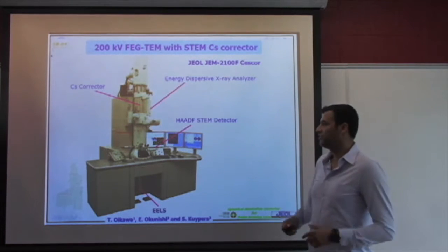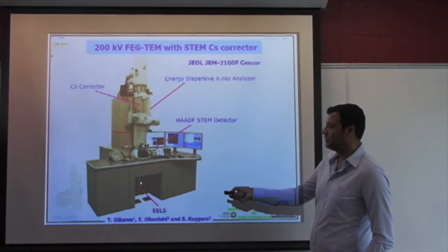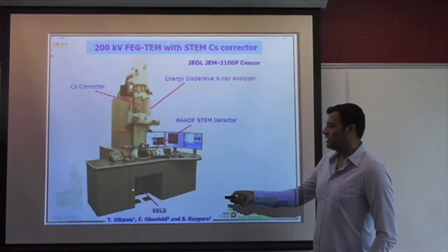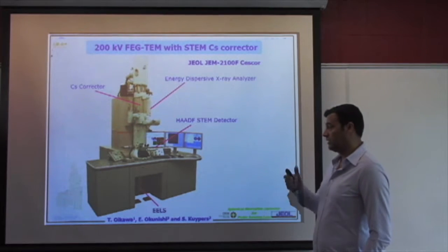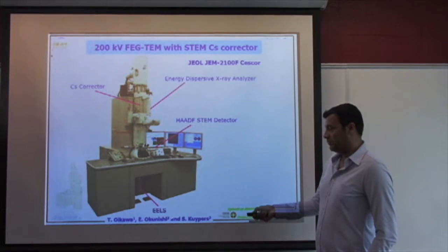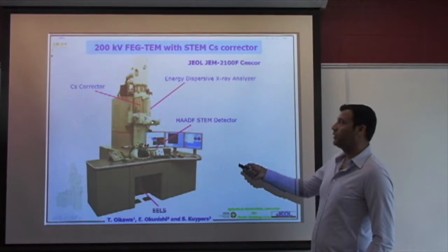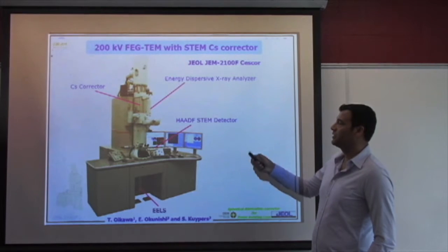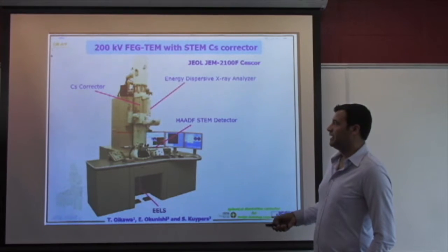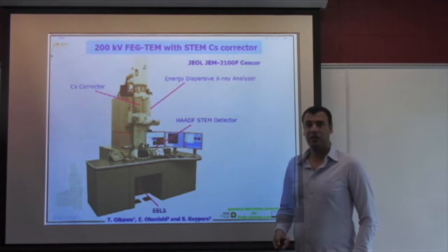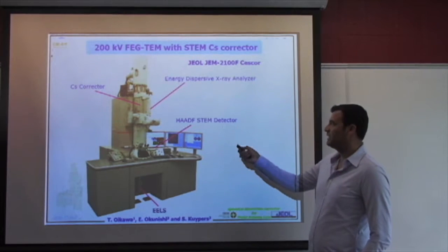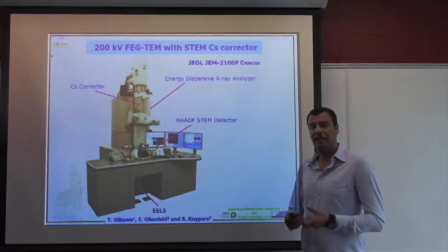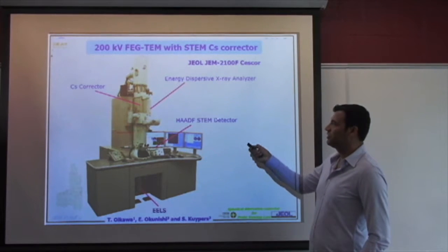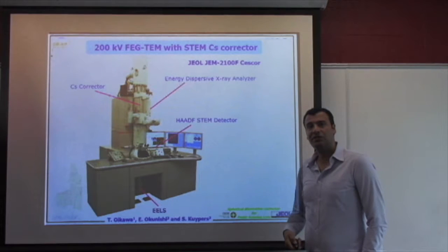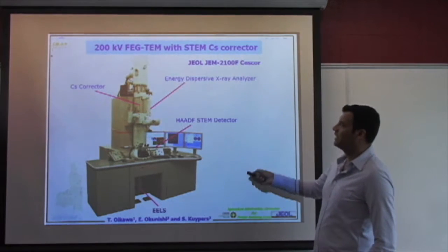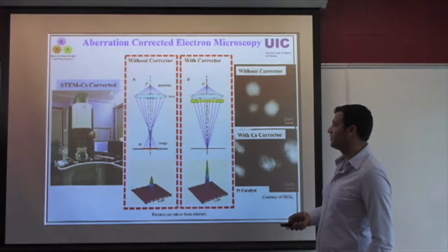That's the overall configuration of the system that you're going to use to understand the fingerprints and the chemistry of your sample at very small scales. You can do EELS. You can also sometimes do EDS using these detectors. And for imaging, many times now we use HAADF imaging, which is sensitive to very heavy elements. There are newer detectors that can do light element imaging. We call it ABF. These can all be used to image the structure.